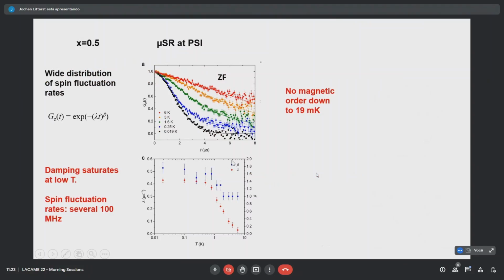Now, what did we find? We made muSR at the Paul Scherrer Institute in Switzerland, and for sure, we don't see magnetic order down to 19 millikelvin for the 0.5 compound. That's just sitting between the opposite cases, between the columnar and the normal antiferromagnetic.